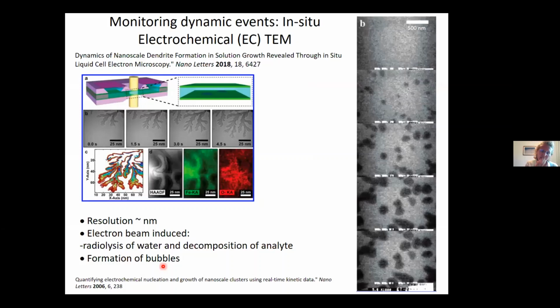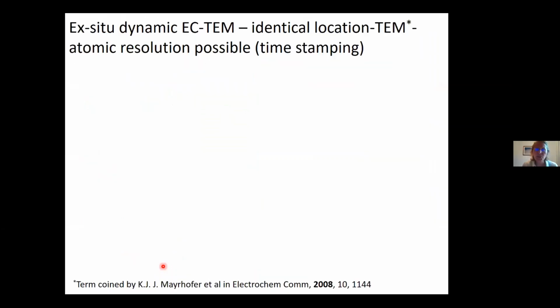But it's really interesting. I want to introduce you to another kind of technique, which is not as well known as perhaps the in situ electrochemical TEM. And this is a technique called identical location TEM. What it does is it's an attempt to get to dynamic information, but while still retaining extremely high resolution of the best TEMs out there on the market, the aberration corrected. So this term was coined by Mayrhofer et al, and it's a kind of time stamping. So it's a stop, start technique.